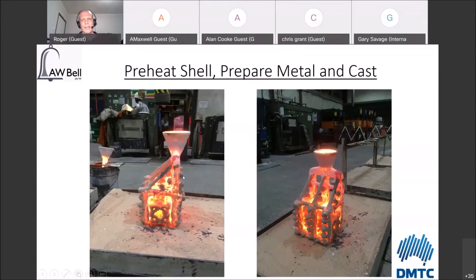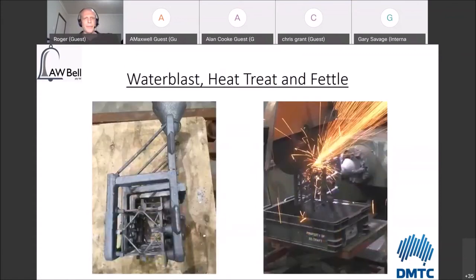So you can see it's end on here and then side on here, very similar to what you saw in the wax stage earlier. Now it's at the point of being cast and ready to be cooled down and have its shell removed. So the first step that happens is water blast. You remove all the ceramic shell with high pressure water, and you can see that the part is inside the runner system here, and held quite firmly within the runner system. Now that is something that we learnt was extremely important.